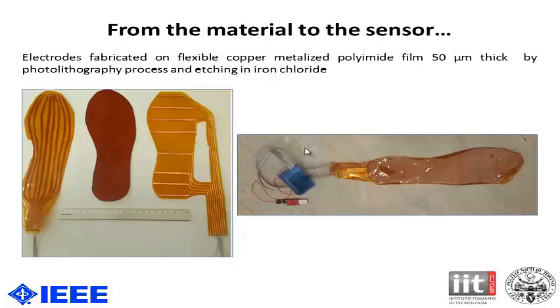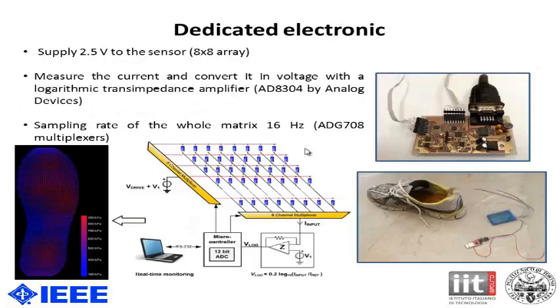The material was then sandwiched between two metallized Kapton layers, which were then photolithographically processed in order to obtain the electric connections. And then the sensor is connected to the electronic part. The electronic part is composed of an 8 by 8 matrix array, and the measurement performed is the measure of the current for each node.